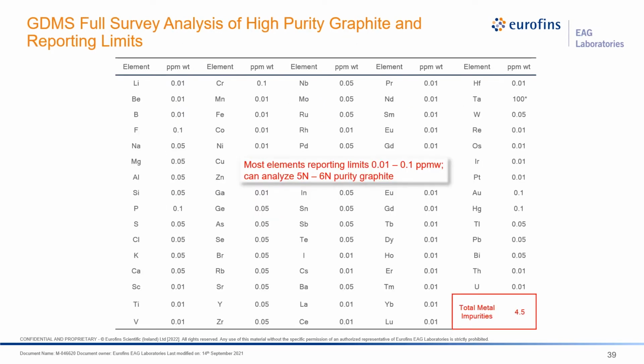GDMS, again, provides a full survey analysis capability for high purity graphite. In general, most elements can have reporting limits from 0.01 ppm to 0.1 ppm. It can easily analyze 5N to 6N purity graphite, with the total metal impurities summarized to 4.5 ppm.